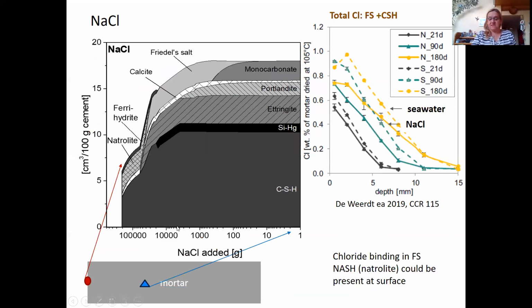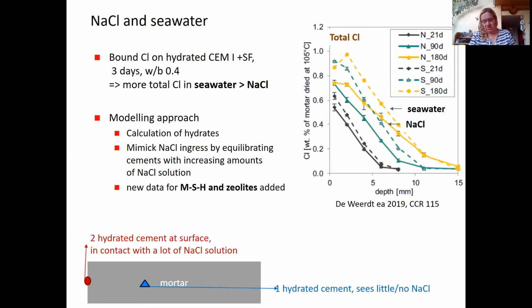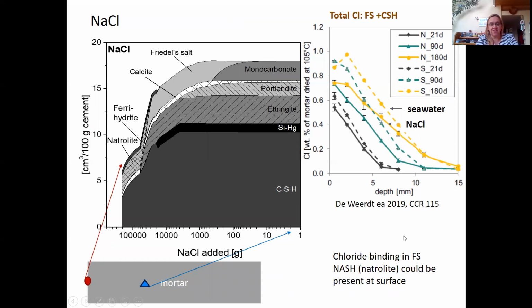We used a simple modeling approach. We first calculated the composition of the hydrates, and then we mimic the sodium chloride ingression by equilibrating our hydrated cement with different amounts of sodium chloride solution, basically with the idea that a piece of cement in the middle sees only very little of the sodium chloride solution, while a piece sitting here on the surface will see a lot of the sodium chloride solution. If we do that, we get a picture like that.